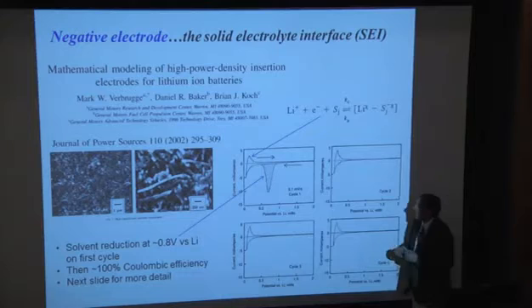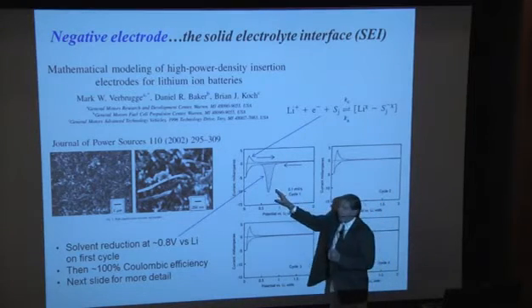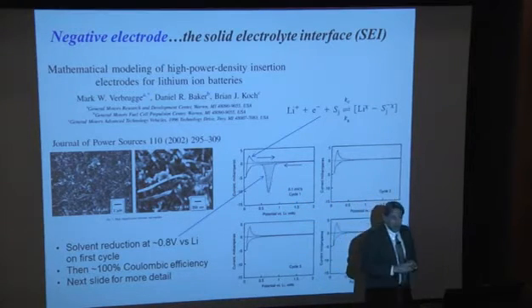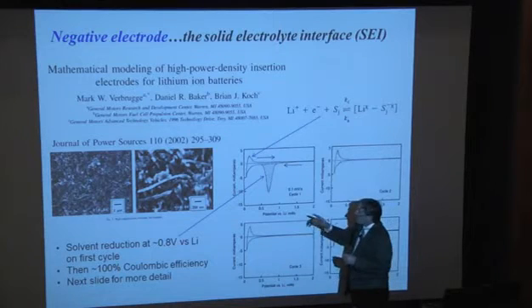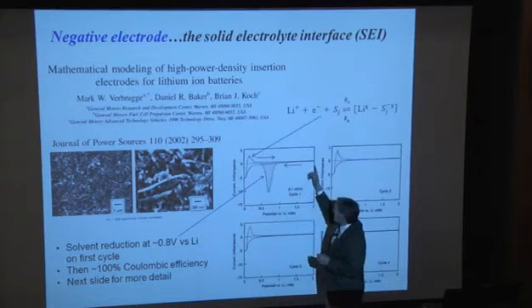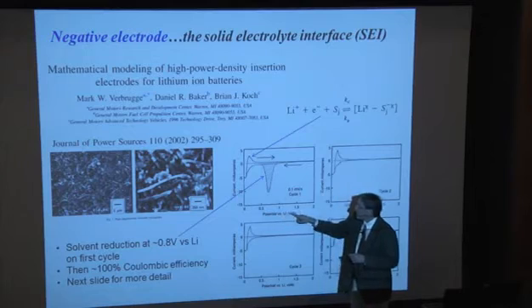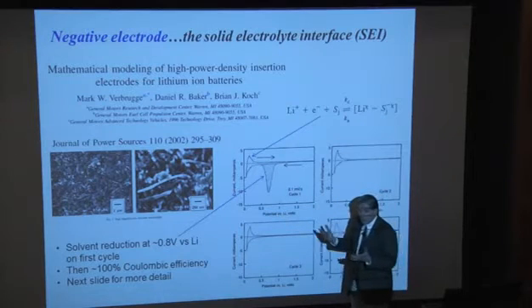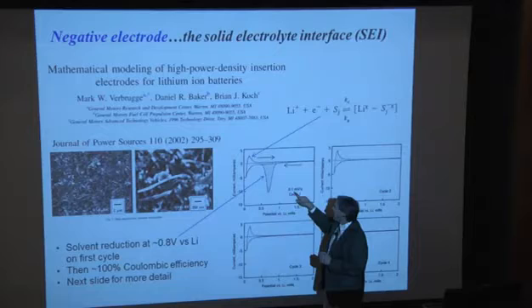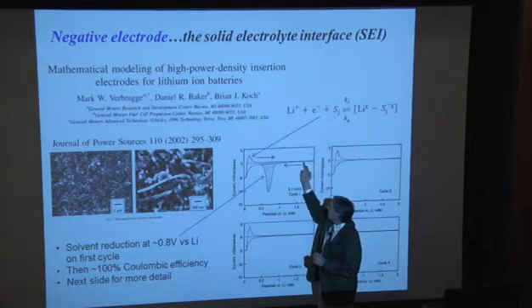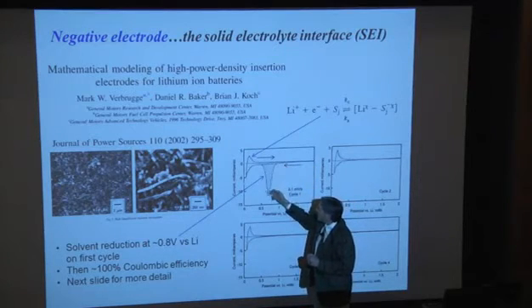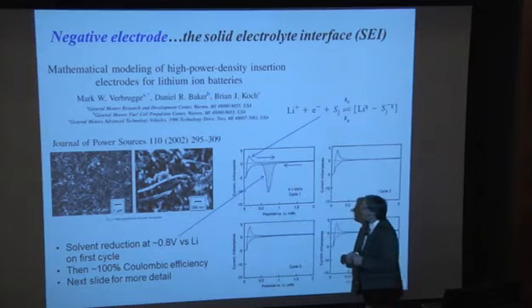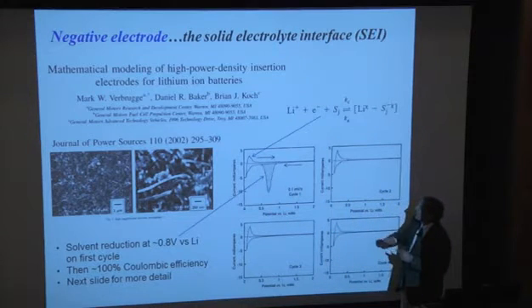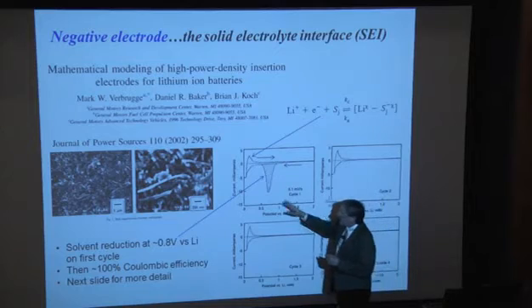That's the degradation reaction. So on the very first cycle, when you condition a lithium-ion battery, what you find is this is a carbon electrode versus a lithium reference electrode. So this is the potential of the carbon versus the lithium reference electrode in a cyclic voltammeter experiment. You scan the potential linearly at 0.1 millivolts per second, no lithium in the carbon. And then you come down to this reduction peak at about 0.75 volts versus the lithium reference electrode. And that reaction, I'll talk about on the next slide, but it's a solvent reduction reaction.